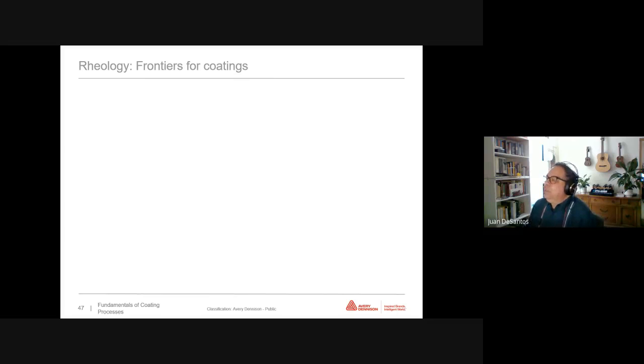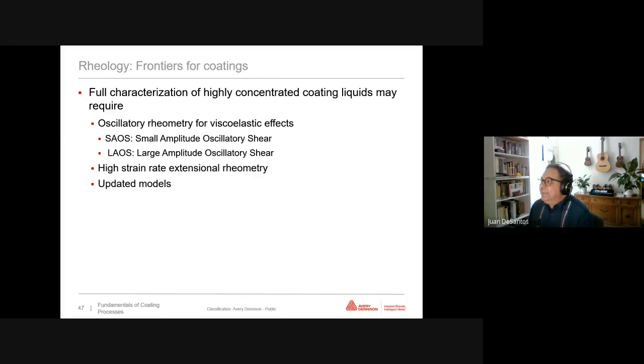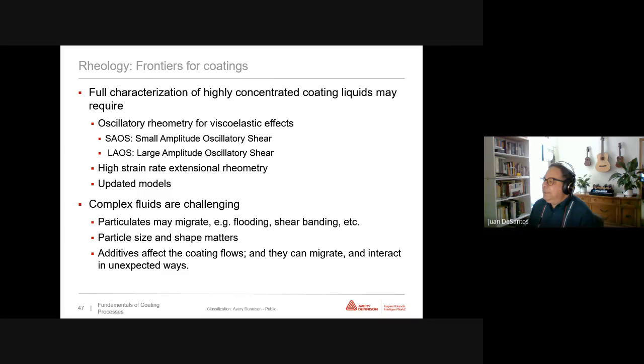Now, there is some drive to use more concentrated coating liquids, as then drying requirements are lessened and the process may be faster, but complex behavior may arise, for example, viscoelasticity in concentrated polymer solutions, and more advanced techniques may be needed both for measurements and models. Complex liquids containing particles may be challenging, as particles may migrate under shear or segregate due to improper stabilization. In all of these, particle sizes and shapes matter. Oftentimes, additives used to ameliorate the problems may cause new ones, as they can migrate and interact in unexpected ways. So in regards to designing coating liquids, the only advice that I will give you is keep it simple, or as simple as possible.